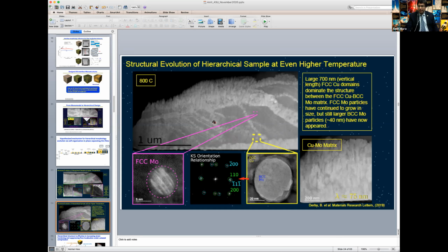Although phase field could be tried independent of length scale, just to see how the morphology will change with different composition. If it was not equiatomic, if it was asymmetric, then what kind of pattern will form? You can even create an alloy and then age it or heat treat it. It doesn't have to follow what is happening in deposition. We think what's happening in deposition is a two-step process. In the first step, you create the moly-rich matrix and those copper-rich islands. Then as deposition continues, there is maybe further microstructure evolution inside those separated domains. So it may be possible to take a copper grain, mix 5 or 10% moly in it homogeneously, and then run a phase field to see how that evolves, independent of length scale.